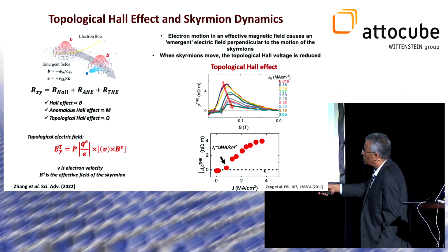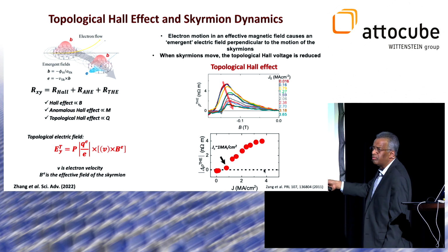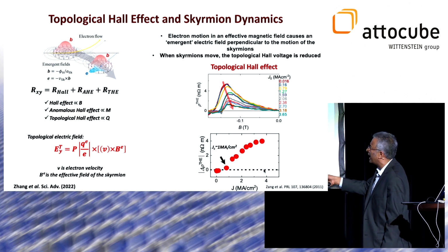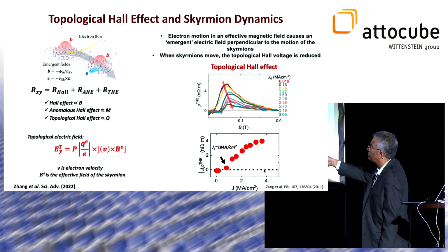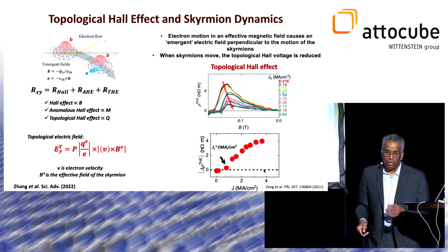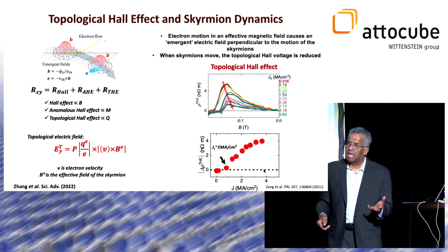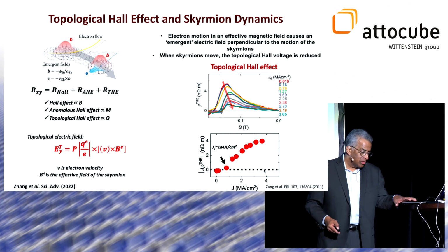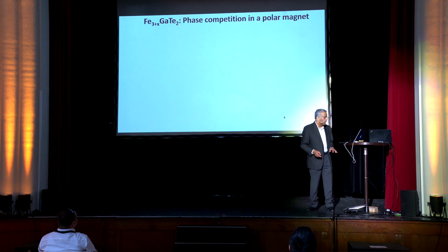Those skyrmions begin to move at about 1.4 or so mega amps per centimeter squared, and then they start to move, and this resistivity contribution comes down. So those are all evidences that you can actually have the skyrmions tuned by the structure, and then you can start to do dynamics with them.